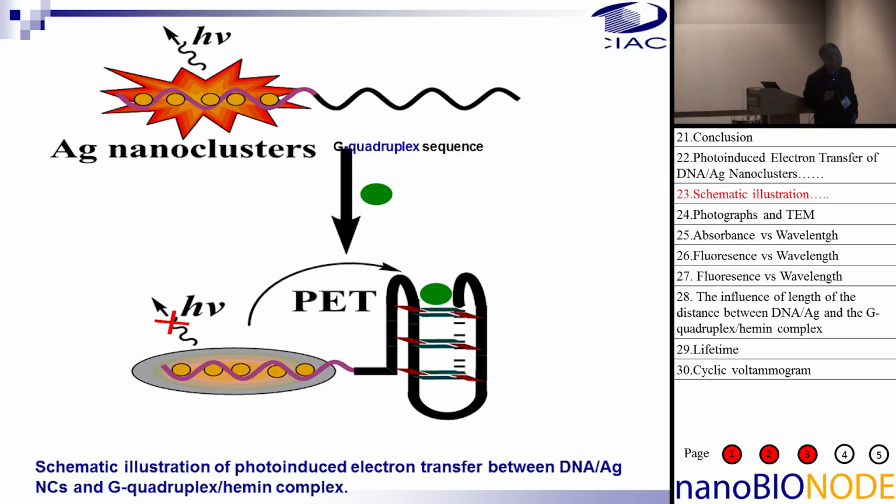So I wanted to say, in this case, because of the ferri and the ferro, and this G-quadruplex, this is the redox as the electron acceptor. Therefore, the photo-electron transfer here quenches, not to the ground state but to this step, and therefore it is the quench effect, and it is related to the concentration, for example, of the hemin.